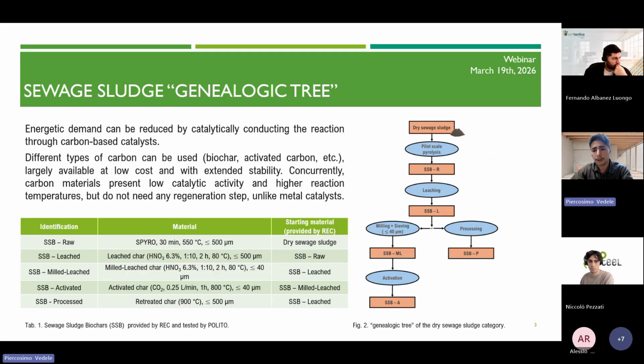From our side, we tested several biochars, so carbon-based catalysts, which were synthesized by REC and which belong to the sewage sludge family. The biochar produced from the sewage sludge was subjected to different upgrading processes to produce catalysts with different characteristics. In particular, the raw char was leached, then milled and sieved in order to obtain a catalyst with a smaller pellet size, and then activated to obtain a material with different morphologic characteristics.